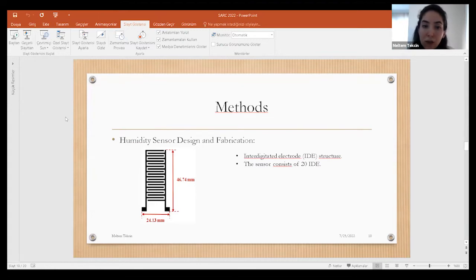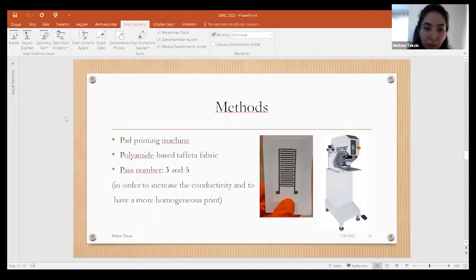Here we can see the humidity sensor design. This design is an interdigitated electrode structure, and the sensor consists of 20 IDE. The printing process was applied on polyamide-based taffeta fabric with a pad printing machine, and 3 and 5 different pass numbers were applied in order to increase the conductivity and have a more homogeneous print.